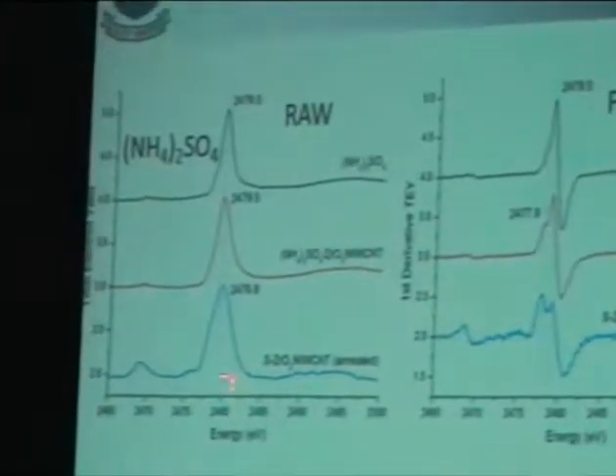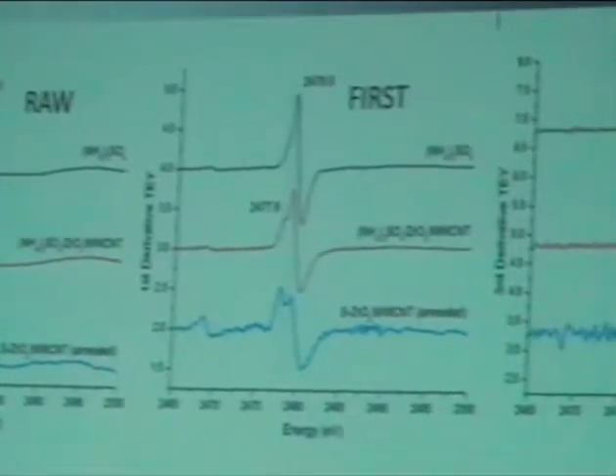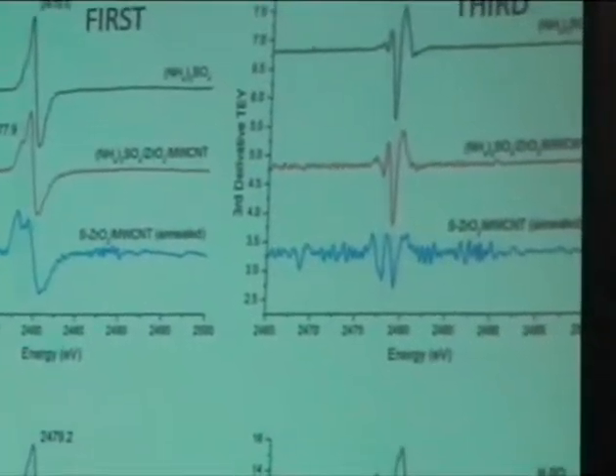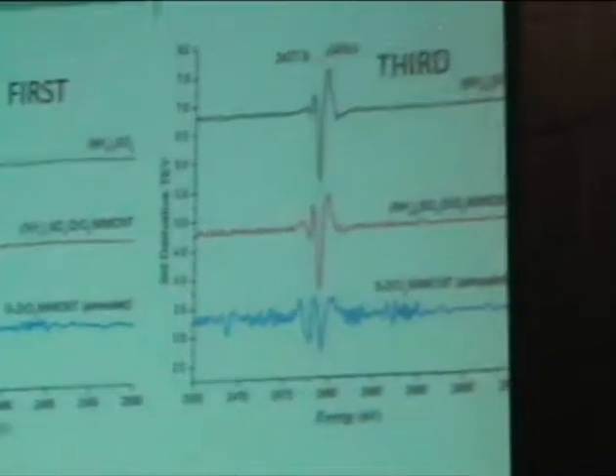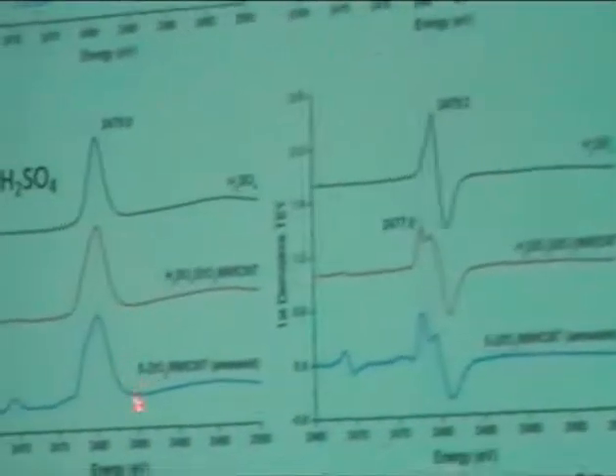It doesn't see much, you don't see much change. And then this is after the annealing, when you crystallize the zirconia and either decompose all the sulfate or a portion of it is still interacting there. The same thing is being shown here for sulfuric acid.